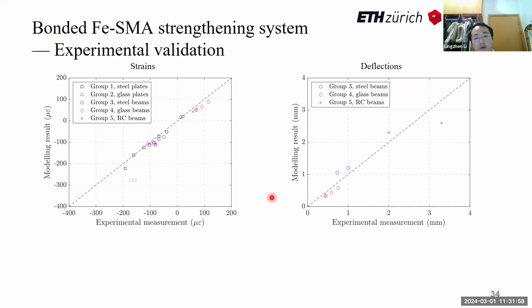Even though this model was derived based on strengthening for steel structures, I also tried validation on strengthened glass structures and strengthened concrete structures. Most of the data supported the derived model, apart from these two dots. I have to say that these two gray dots with the huge arrow contain some deficient experimental design in my cases. But the rest, nearly 20 dots, supported the accuracy and the efficiency of the model prediction.